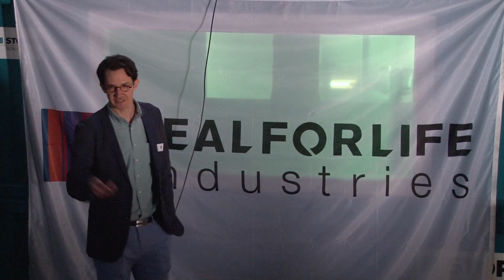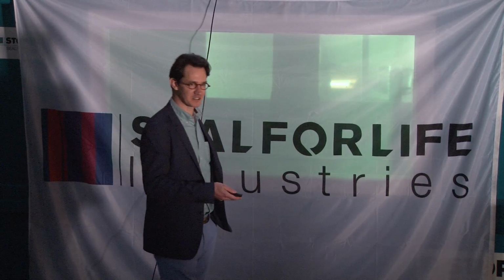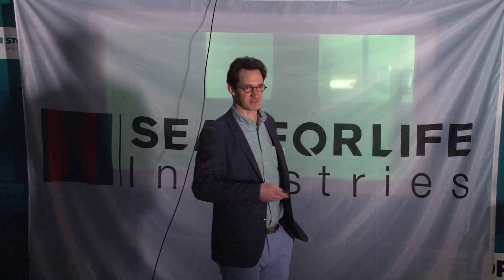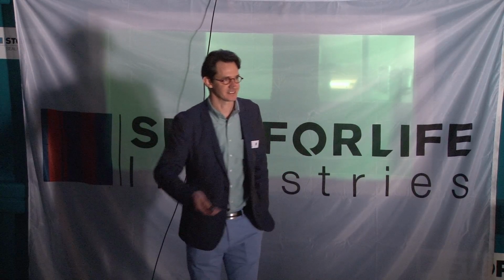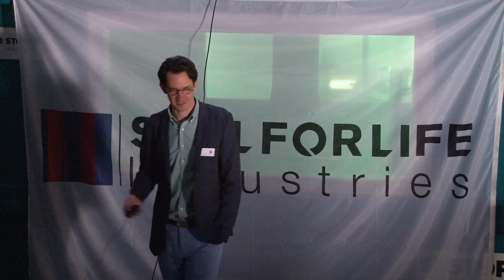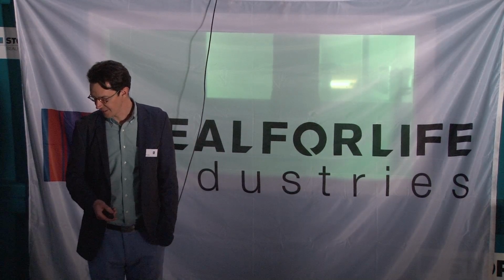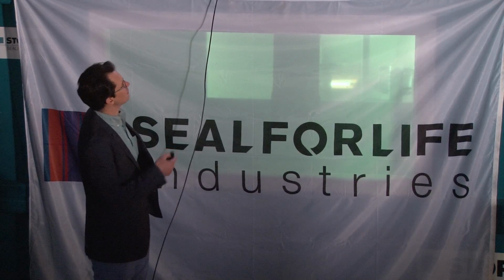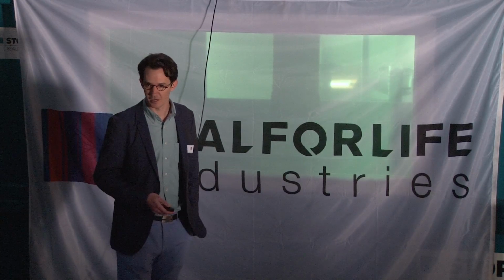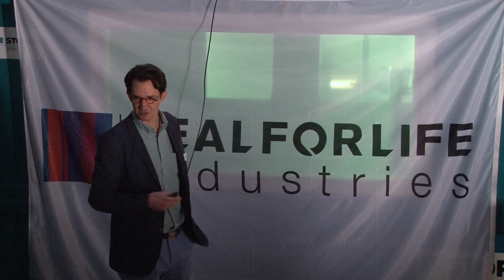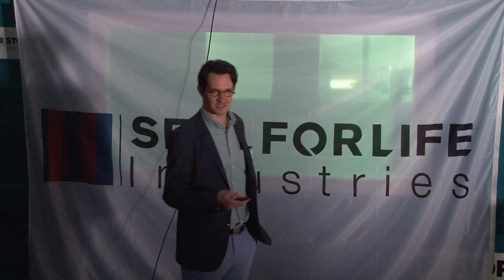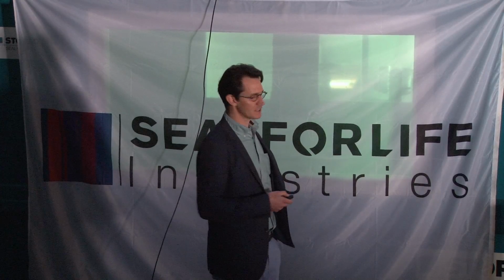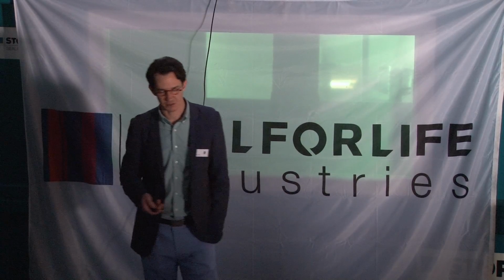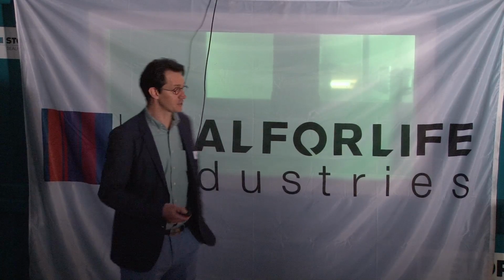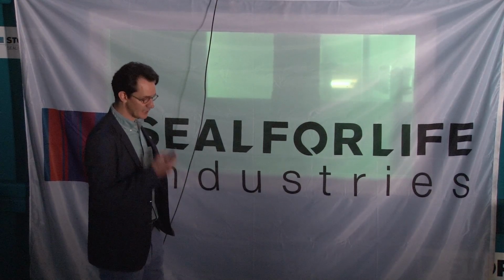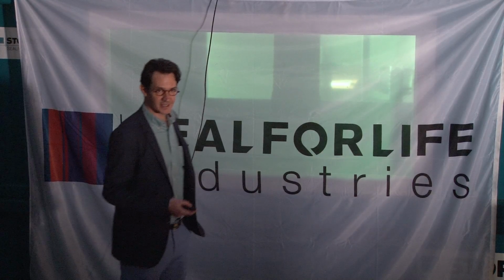So what's the potential of the market? Again, huge. Because if the technology is recognized by everyone, if everybody is interested to seal for life, not for now, then obviously we can offer a solution for life. What does it look like? Well, this is an example of what a pipe is buried with. It shouldn't be like this. There's a procedure which tells you exactly the sand that you should use to protect your pipe. But in reality, you just bury it with whatever is available, which are mainly rocks, and you destroy the coating. Once you destroy the coating, and if you broke the coating, there you have a problem.